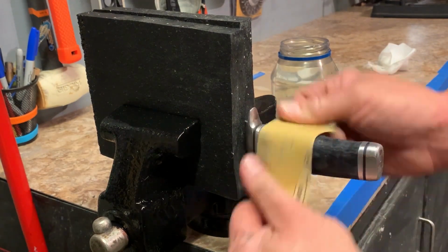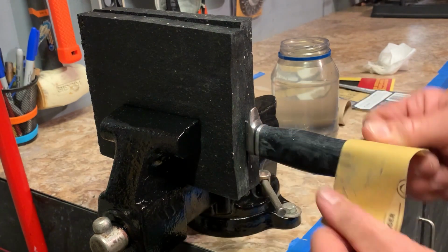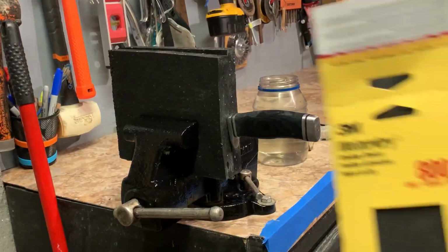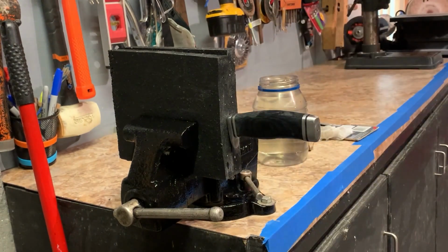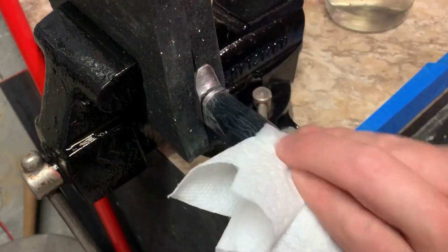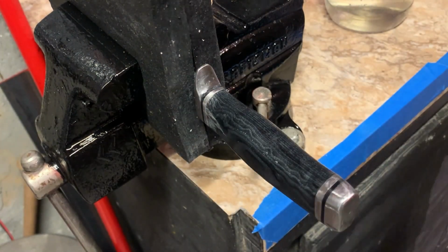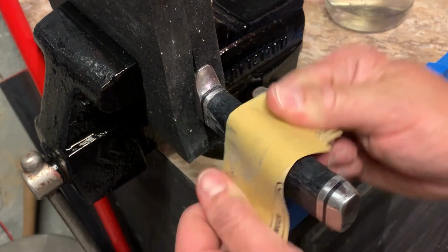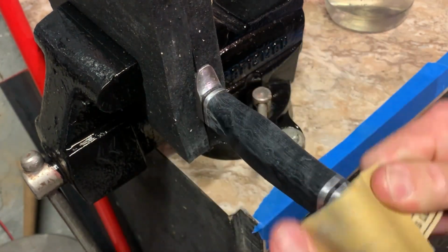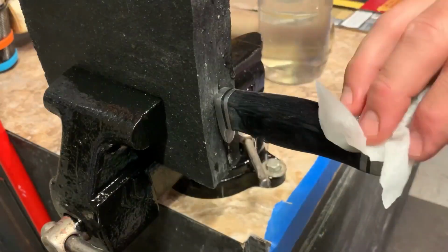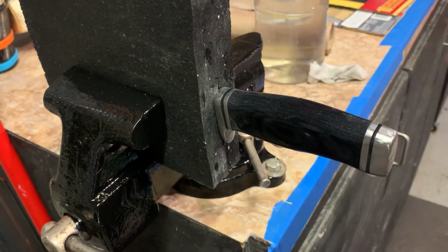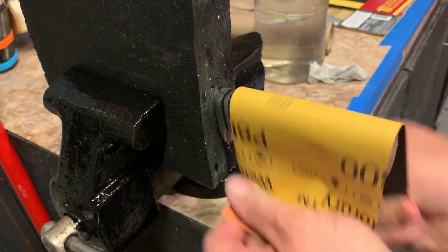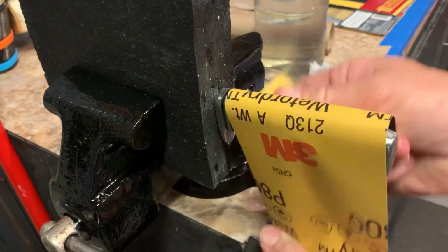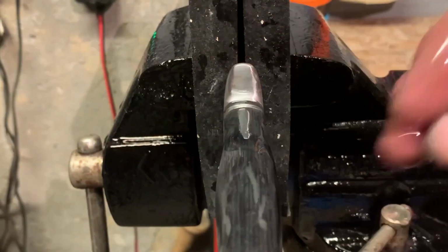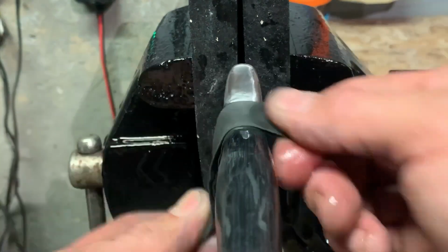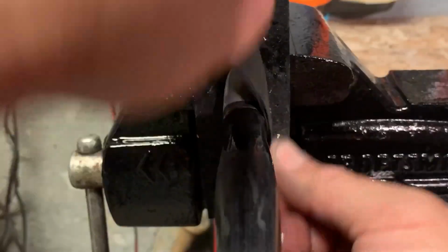So now that I'm all set up in that nice new vise pad, I'm continuing to polish the handle. Next I took it up to 800 grit and ultimately to 1500 grit. And once I get up around this fine, I usually wet sand with water. I of course left the pommel and guard at a 1500 polish, but on the micarta I ended up going back down to 400 grit because I began to realize that the higher polish I achieved with this black and gray alternation, it became harder and harder to tell the difference between the two colors. Not only that, I feel like if you take micarta up to too fine of a polish, then you start to lose the nice gripping quality that it has. So for this micarta, I arrived at the best combination of looks and good non-slip grip with 400 grit.